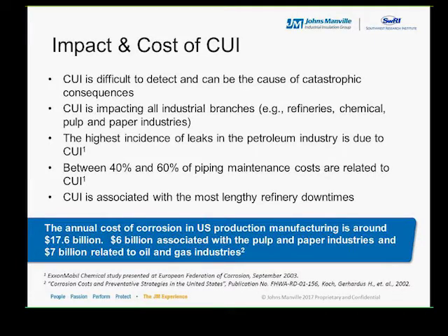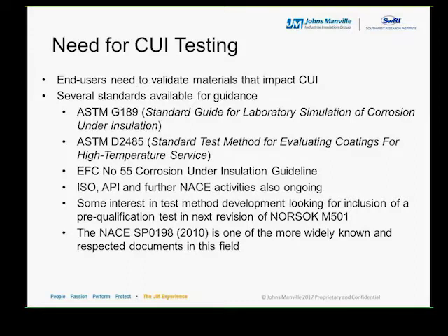Need for CUI testing. The current standards related to CUI are either difficult to use or in many cases lack relevancy. Coating and insulation vendors started to use internal test methods to evaluate CUI performance at elevated temperatures. The main issue with those tests is that in some cases the test method is so aggressive that systems which have performed in the field for years suddenly look really bad in the lab and vice versa. The SP0198 document offers a true view of CUI mechanisms, as well as directions on coating systems and the limitations of certain coating technologies.